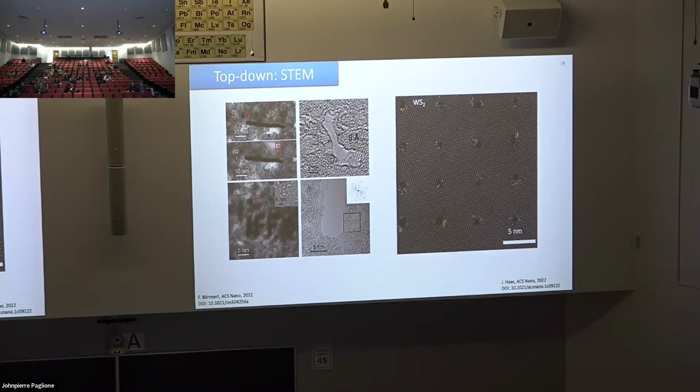When making each of these holes, you just hold the electron beam steady while it goes through. There's no moving back and forth, up and down, or sweeping it while you're making each hole. Depending on how big your spot is, I think these ones are moved in a small circle. But in principle, you could just keep the spot fixed and you get something like a 2 nanometer hole. But it is also a slow process if you want to make larger holes. But the edge would definitely affect the material, depending on the magnetic field applied, right? Probably, yeah. I'm not exactly sure how.